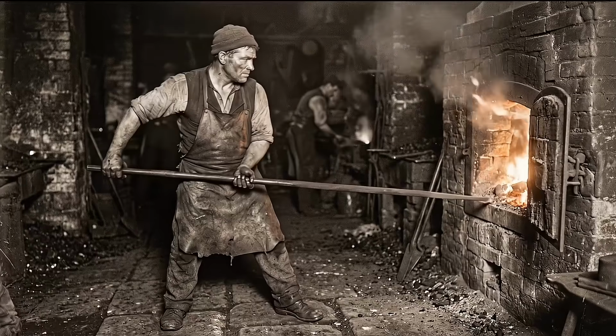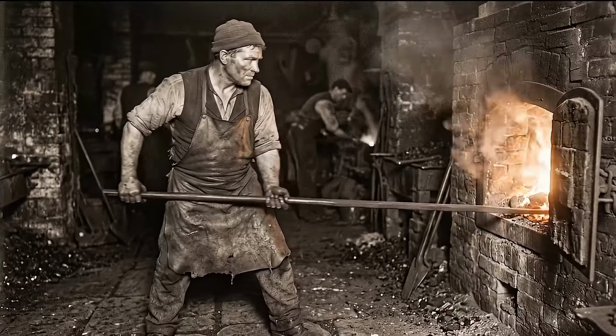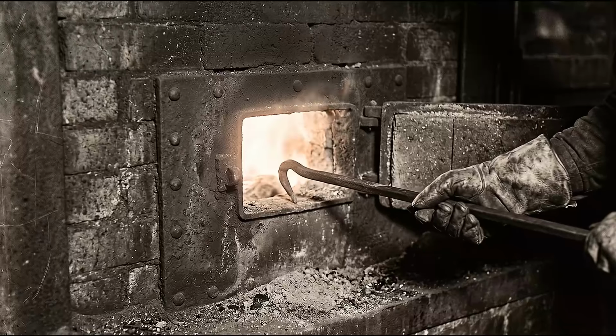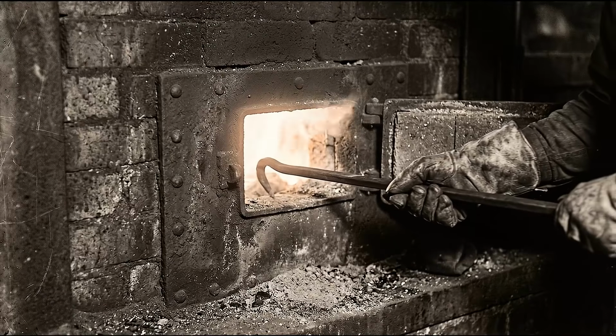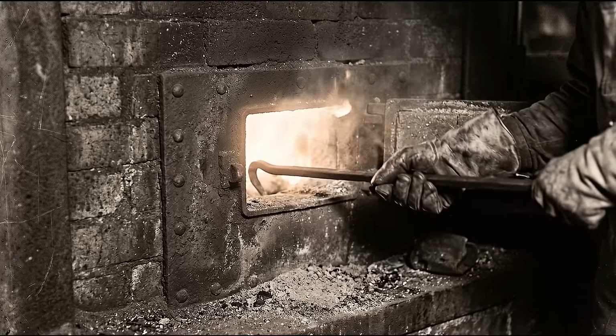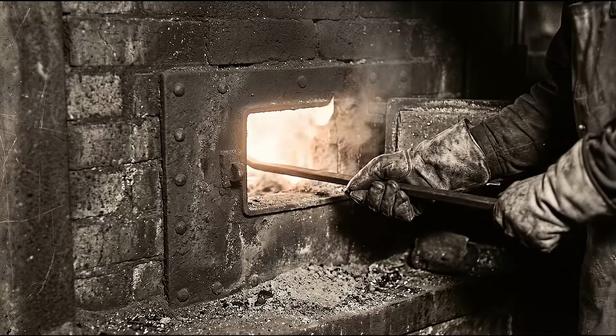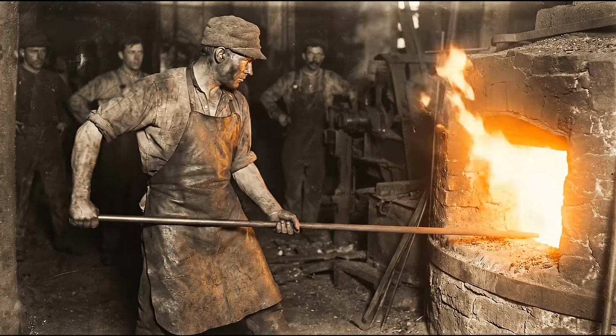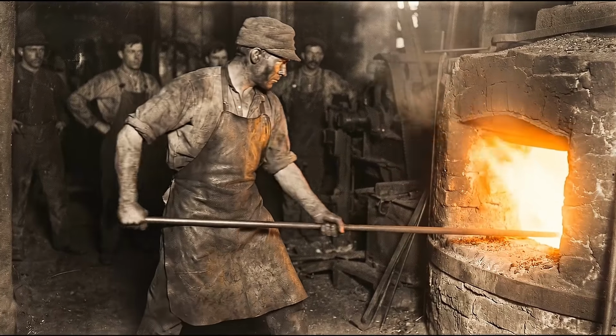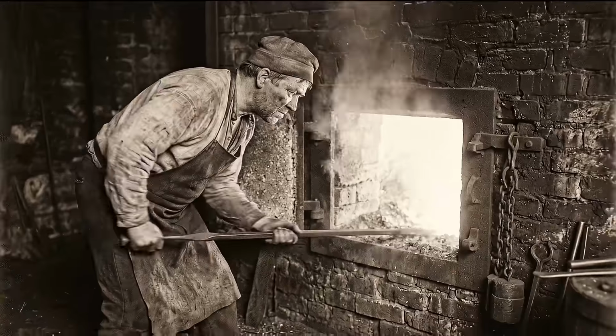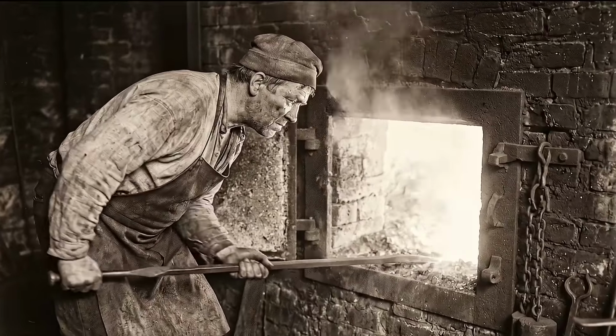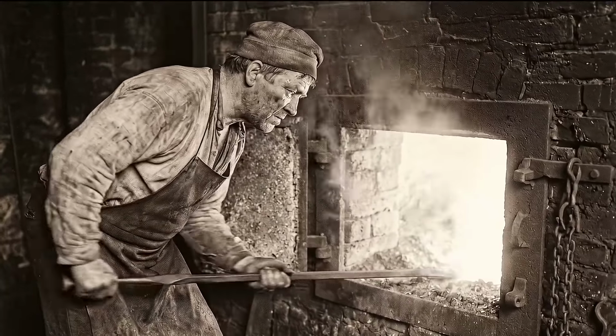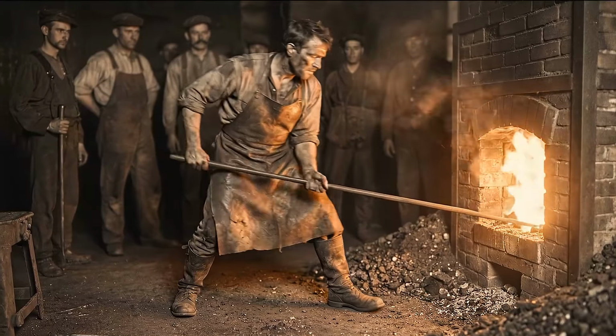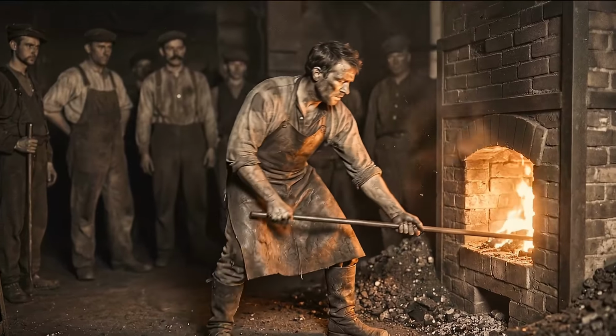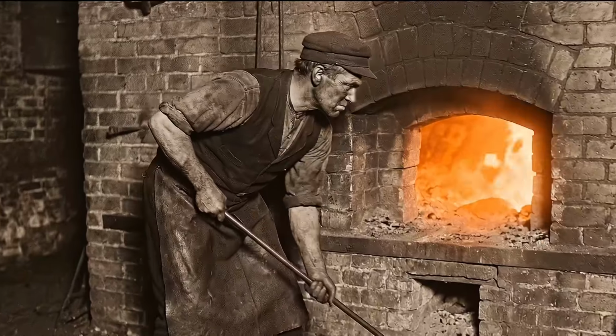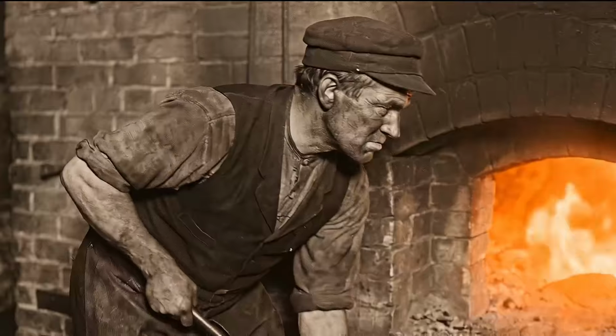And then came the hardest part. The puddler picked up his rabbling bar, a long iron rod with a hook or a flat blade at the end, pushed it through a small opening in the furnace door, and started stirring. The goal was to expose as much of the molten iron to the air as possible, so the oxygen could strip out the carbon. He raked the metal back and forth, folded it over on itself, dragged it from one side of the hearth to the other. It was hot, heavy, miserable work, and it got worse as it went on.